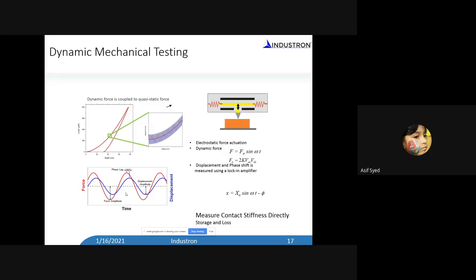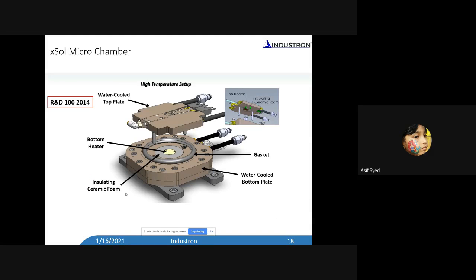But now, let's say you wanted to change the temperature of the specimen, then we can do the experiments as a function of temperature. So we also developed a heating stage. I'm just going to give you a one-slide overview of the heating stage. It's basically a two-part stage. There is a top part, which is also a heater, and a bottom part, which is also a heater. So you put the sample in between these two heaters and sandwich the sample so that you heat the sample from the top as well as from the bottom.